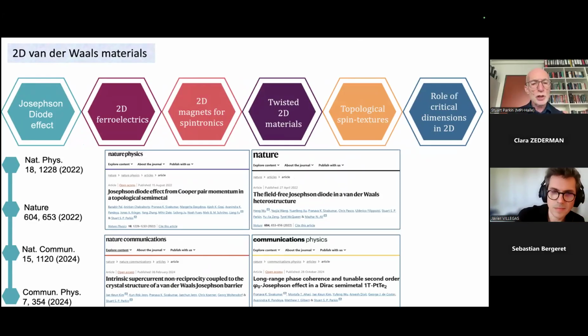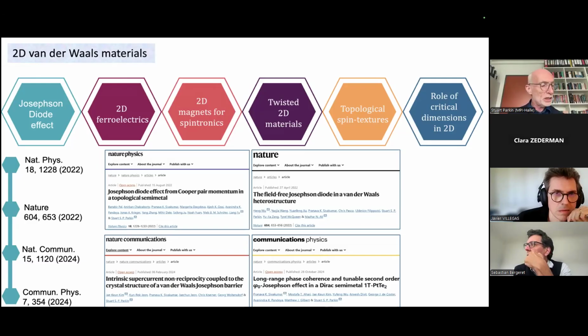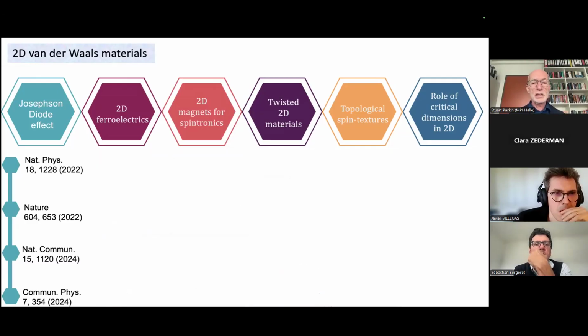And what we were able to show is that we could see a very interesting diode effect by utilizing a special 2D van der Waals material, nickel ditelluride. And later on, we showed we could see similar effects in a closely related material, platinum ditelluride. So I'm going to come back to that. And one of our most interesting works is a recent work from last year, where we believe we demonstrated that this diode effect we see is intrinsic. It's an intrinsic effect and not extrinsic, as claimed now by many groups. And I want to discuss these 2 experiments after this brief introduction to some of our work on these 2D materials.